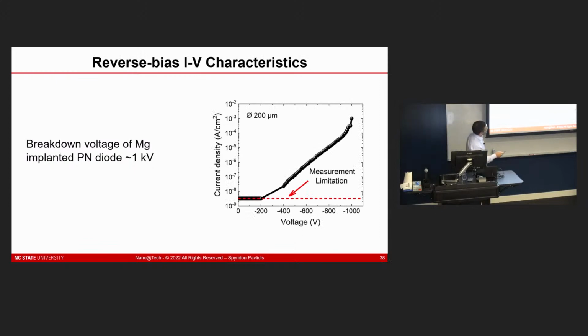And so this was a reverse bias characteristic that we got for this device, and you can see that it's breaking down at about 1 kV. So this was one of the first devices that we were able to make. Very, very happy with this result originally, but we knew that there were a lot of problems. And what I'm not showing you here, for example, is what happened when we make Schottky contacts on these samples that went out for annealing. So we had good breakdown voltage, but the surfaces for the formation of contacts were clearly not ideal for us. And so one of the things that we've been doing over the last couple of years is thinking about different surface treatments that we can use to improve the performance of these devices.